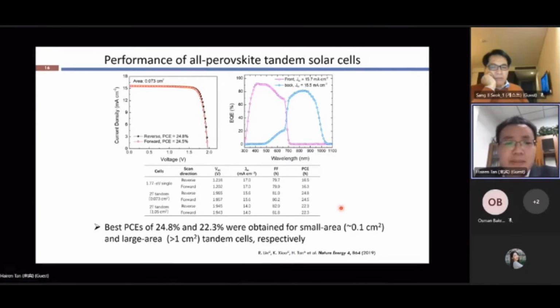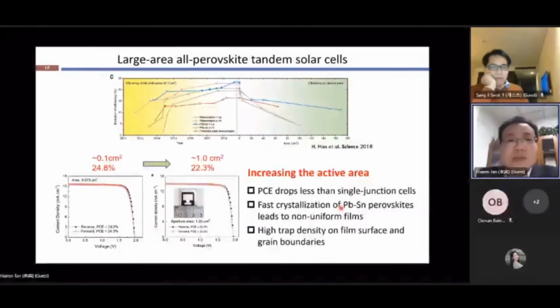It seems that we can even make larger area tandem devices. But still, we can see that if we increase the small area lab devices up to 1 square centimeter devices, we still lost 2.5% absolute in efficiency. And this is challenging not only for tandem devices, I think it is also for single junction perovskite devices. So for tandem devices, to make larger area devices, the challenge is that the faster crystallization of this mixed lead-tin perovskite material usually results in non-uniform film. And also it will generate high trap densities on the film surfaces and the grain boundaries.